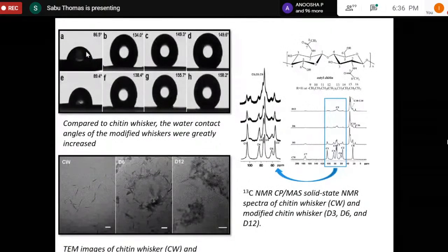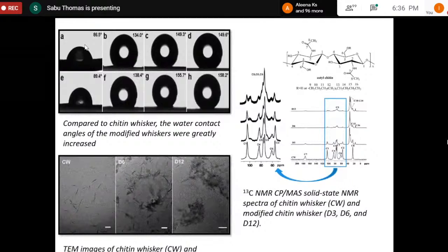Look at this, this is chitin. This is a neat chitin. The contact angle is low. It's hydrophilic. And if you put this alkyl group on the surface of chitin, it becomes hydrophobic. And you can make a superhydrophobic material. 158.2 contact angle.